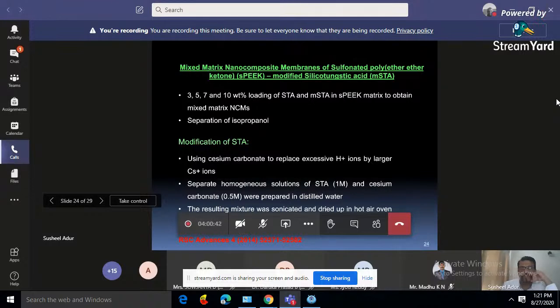And modification of STA, once again, the process of modification is entirely the same, but instead of ammonium carbonate we have used cesium carbonate here, because cesium carbonate is quite appropriate compared to ammonium carbonate. Therefore, we have used cesium carbonate. Cs plus ions will replace excessive protons, and then we get a modified STA, which is much stronger compared to just STA. Just STA, if we use it even in polyether ether ketone, it will leach out, and the membrane performance will be quite lesser. And the same process is involved for preparation of STA, modified STA.